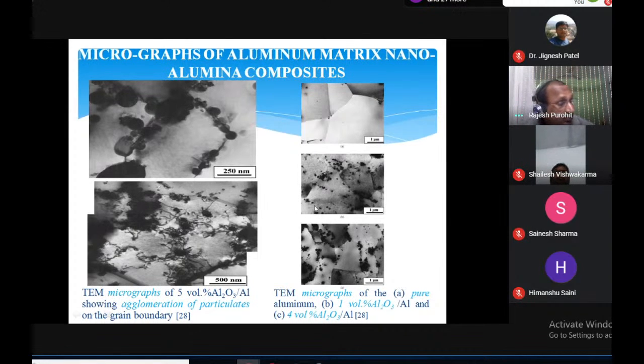And on the right side, we are seeing again a TEM micrograph of the pure aluminum. The upper one is for the pure aluminum, and the next figure, B, is for 1 volume percent of nano alumina, and the bottom figure is for 4 volume percent of nano alumina. Here also we are seeing that particles have got assembled on the grain boundaries. So these are the TEM micrographs, high magnification micrographs. In TEM we can get more magnification, and we can get a clear picture of the structure, the microstructure.